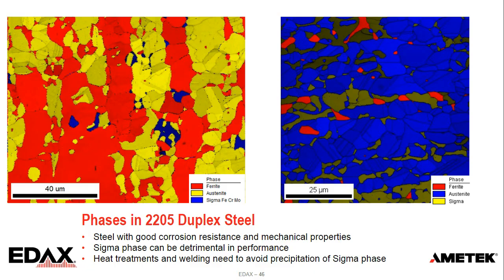So when they heat treat the sample and weld the sample, they try to control the conditions to avoid precipitation of the sigma phase. And so these are two different examples of the 2205 that were heat treated a couple of different ways to measure the amount of sigma that was present. So we can see, on the left, the sigma is shown in blue. Sorry, these are not the same color scale. The sigma is yellow on the right, and you can see the different amounts that are present.